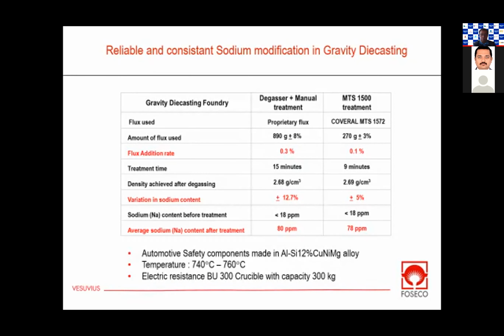In this typical case shown here, we go from 0.3 to 0.1% addition using our MTS process. So for the foundry, they will get the same quality, but there's going to be a significant reduction in cost in the addition of the sodium and the flux. So this will be a benefit for those foundries.